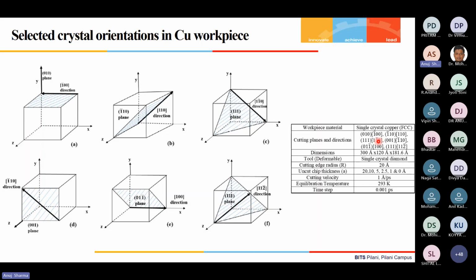Similarly, I carried out the cutting simulation for different crystal orientations of the copper workpiece. Six different orientations were considered for this simulation, and different uncut chip thicknesses were taken. Other parameters were the same, but these 2 things were changed. If we take this orientation, that means the 010 plane and 100 direction, similarly we can change the orientation of the cutting plane and direction.